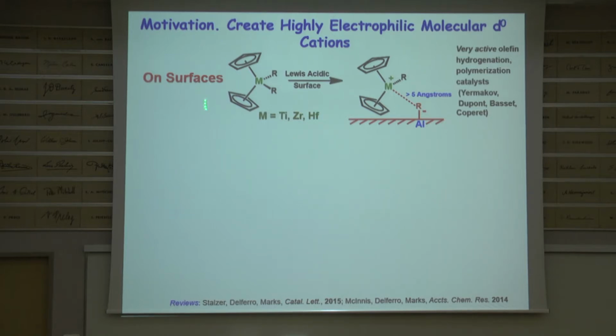So with some solid state, high resolution NMR equipment, relatively primitive at that time, we could see that this molecule on the surface turned into something which we drew as having a methyl anion or an alkyl anion transferred to Lewis acid sites on the dehydroxylated alumina. I first proposed this, I remember this very well, at an ACS meeting, and this is a 14 electron d0 cation. And the response of the audience was sort of like, get this guy off the stage.